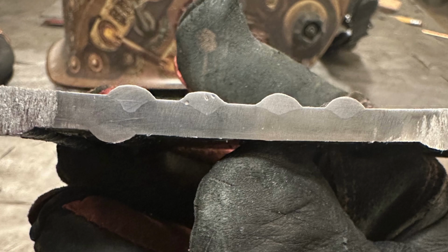Again, if I had to take a guess, I think it's just that the values weren't suitable for the thickness of the plate, and the solidifying weld just trapped that gas in there. Now, the third and fourth passes, which were done with gas shielding, again, I would say without question have less penetration using gas than without it. But the overall bead, toe to toe, seems to be more or less consistent in average penetration. So a little bit more penetration out by the toes, less in the center. Not what I expected. Again, no evidence of porosity on the gas shielded at all. So that's interesting.